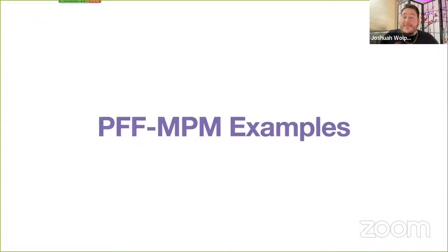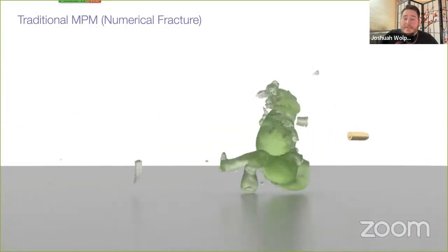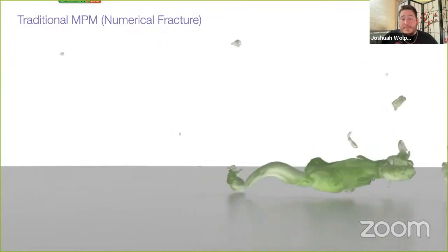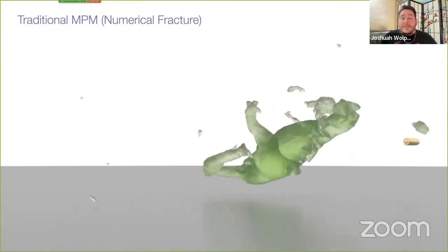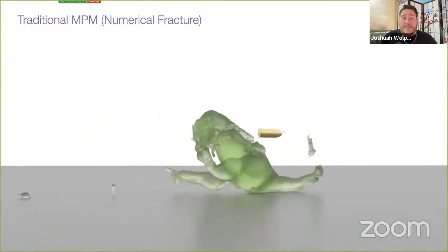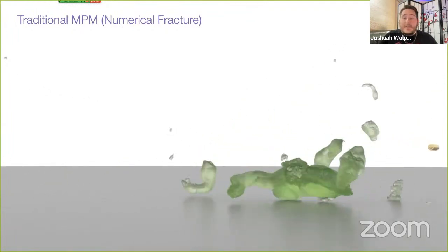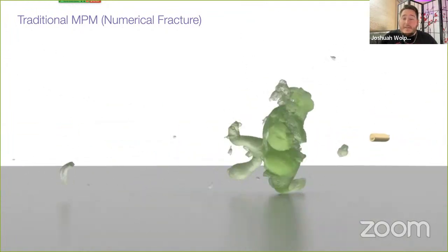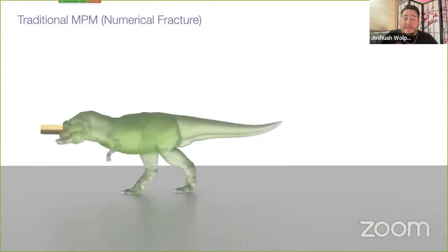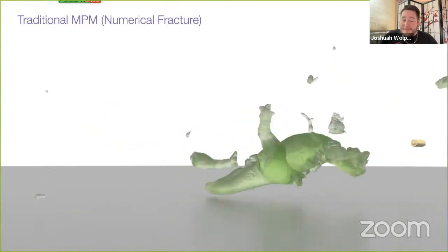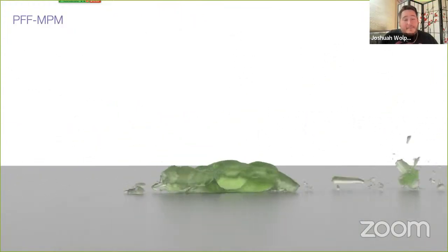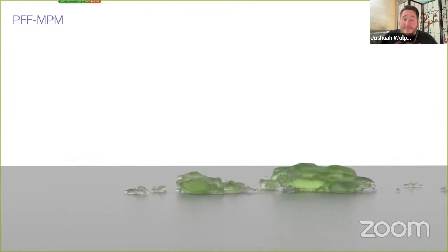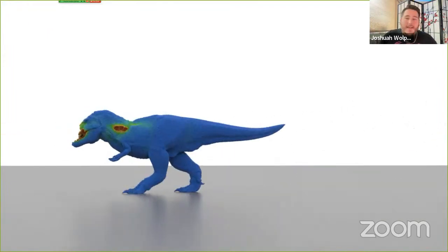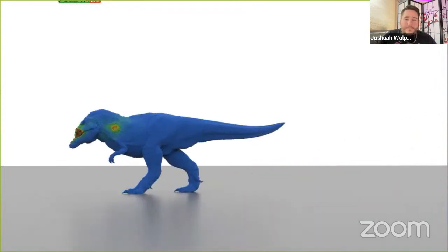So let's take a quick look at some of the effects we can achieve with PFF-MPM. So here, when we shoot this Jello T-Rex with a bullet using traditional MPM, the fracture pattern's at the mercy of unpredictable numerical fracture, which is a unique type of MPM fracture that occurs when material is forced to tear non-physically. And we'll actually discuss numerical fracture more later because it's going to become important. However, using PFF-MPM, we get the desired trajectory through the T-Rex. And here we again visualize the phase field to show crack formation and propagation.